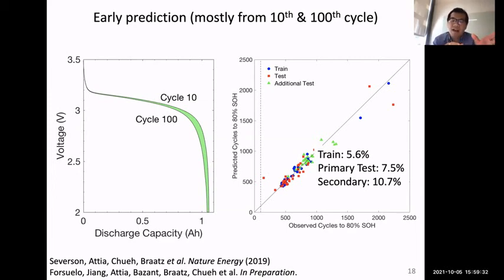So the plot on the left shows you how the voltage of the battery has evolved with age. You can see that the capacity hasn't changed very much, just about 1%. But the voltage has changed quite a bit because the resistance of the battery has grown. So what we did was we computed the evolution of the voltage curves of the battery between the 10th and the 100th cycle.